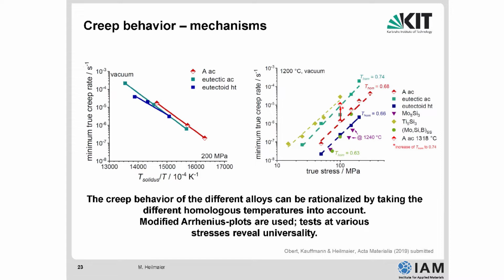Actually, the red alloy falls exactly on the line of the green eutectic alloy, meaning by definition the creep resistance is not different if you compare it in a physically straightforward way, in a physically related way, meaning at the same normalized temperatures. The creep resistance, of course, is better when you let an alloy creep deform at a low absolute temperature with a high melting point.